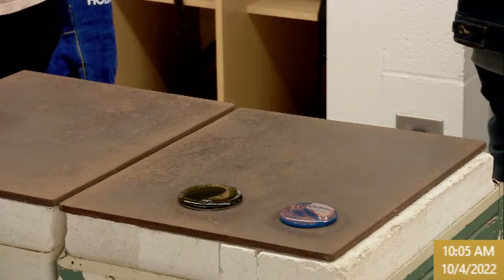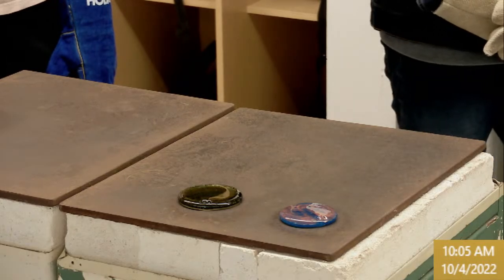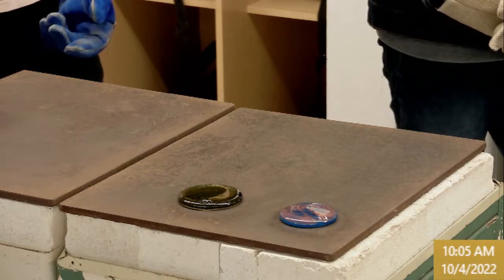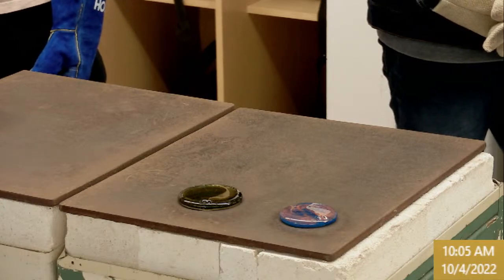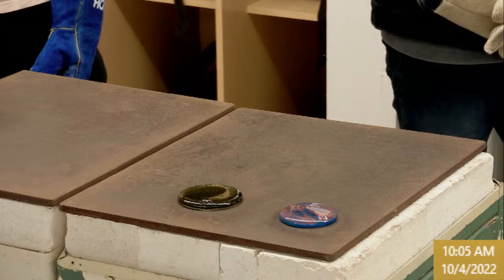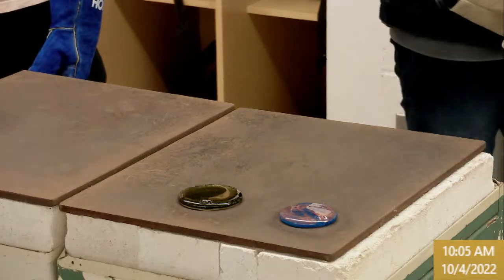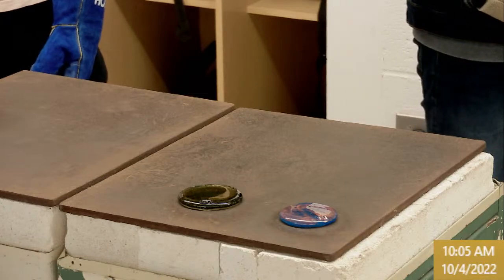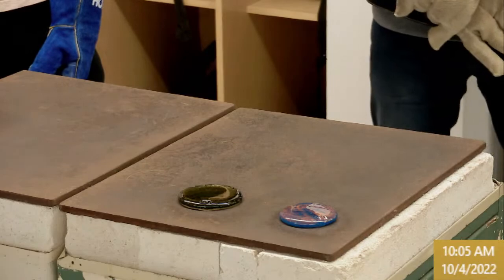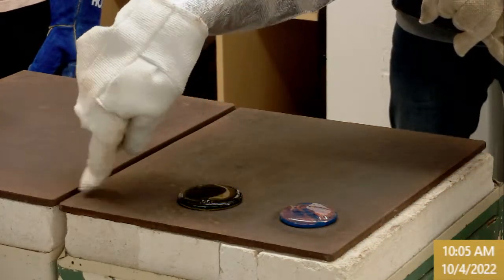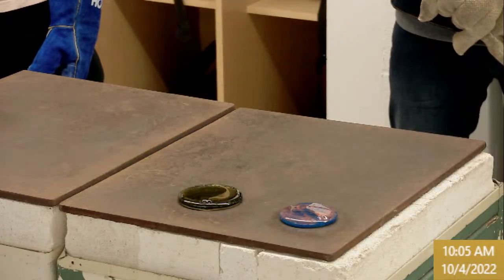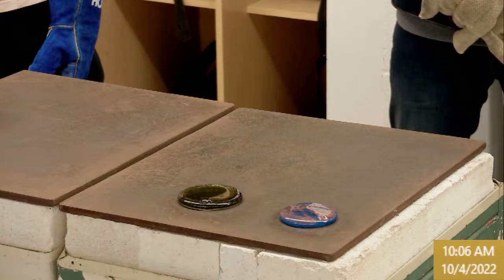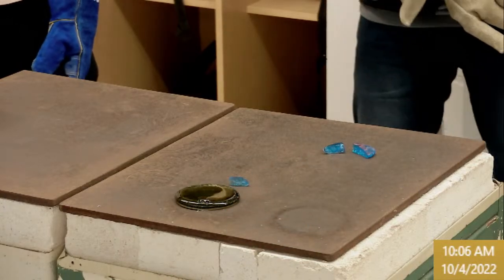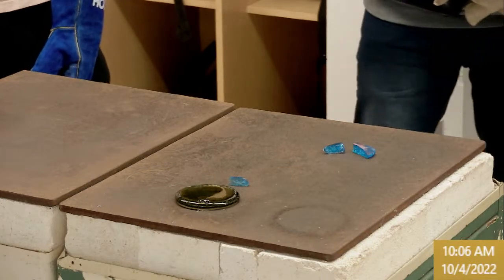It's 40 grams Mason sand, 52 grams of a high purity Granusil, high silica sand. So it's going to be medium impurity there for that combo. 47 sodium carbonate, 25 crushed limestone with 0.09 chrome oxide. We're pulling from the middle. That chrome oxide should make it look green eventually. But chrome in particular does this interesting thing where it starts brown and then flashes to green at around 400 or 500 degrees Celsius. So it'll start one color and then fade to green, and then the green locks in. So that's what I was talking about.